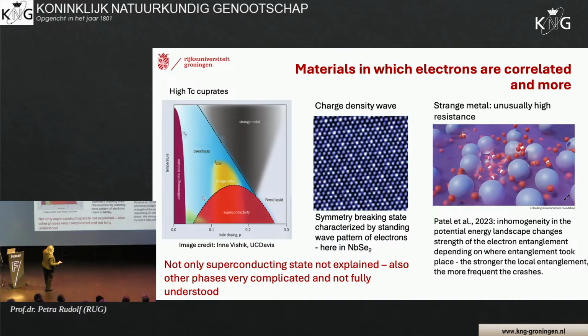Then if you go down, you get magnetic material, you get a strange metal. A strange metal is a metal with an unusually high resistance, much higher than normal metals. And that is because you don't have all the electrons which are entangled, which talk to each other in the same way, but you have local parts. So you have a sort of Mexican wave. In certain parts, the people are excited, and in certain parts they are not. So they communicate differently in different parts of the solid. And then the stronger the entanglement, the higher the resistivity. So this is a strange metal. That is what you have up here.